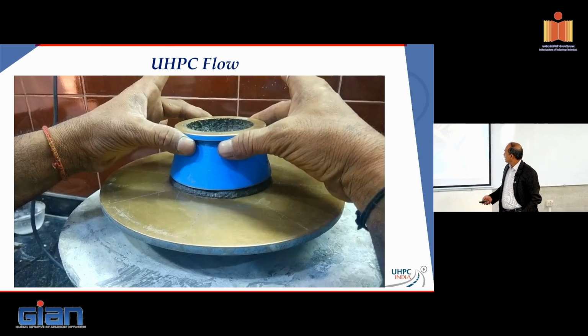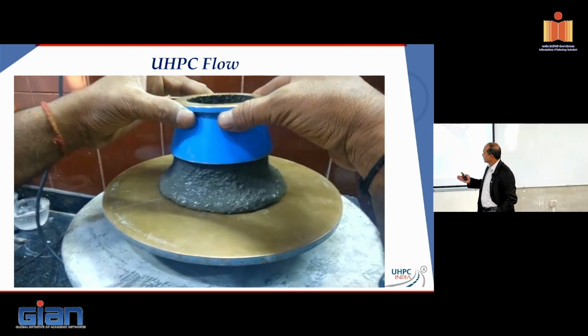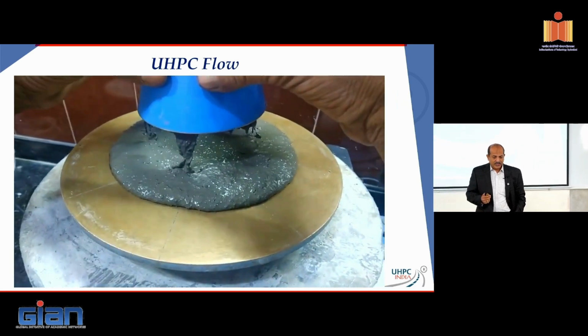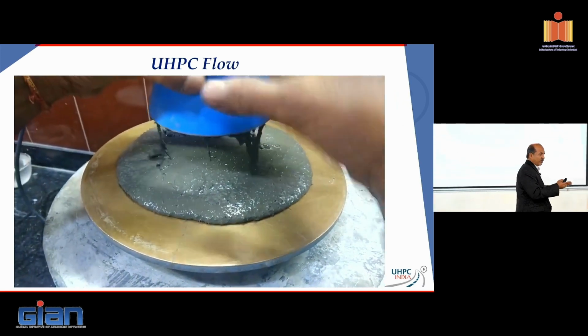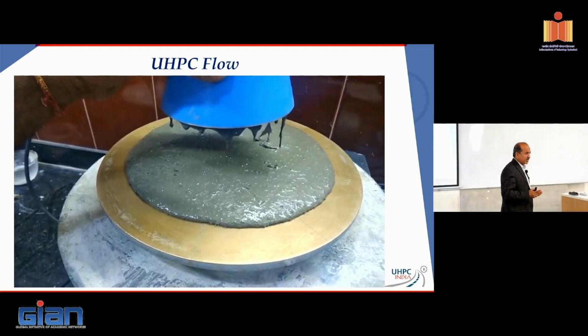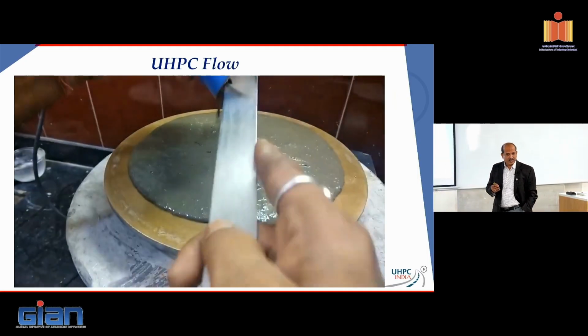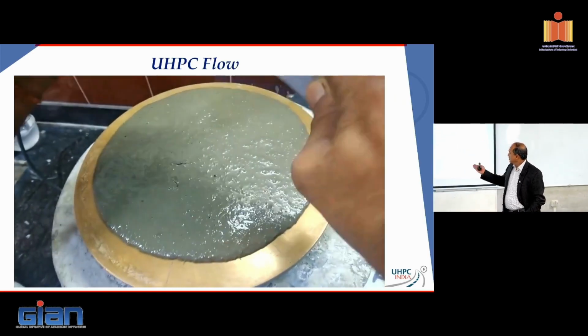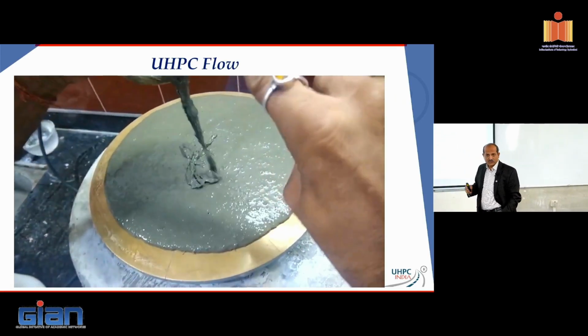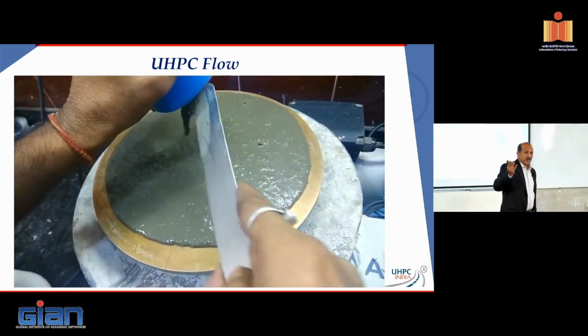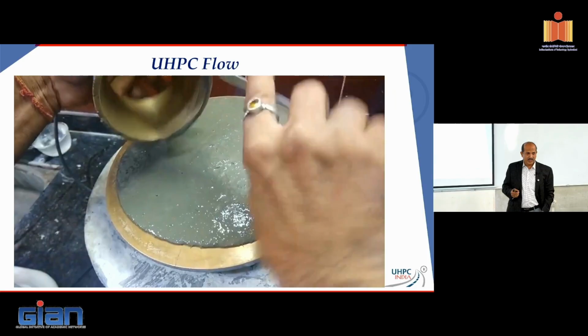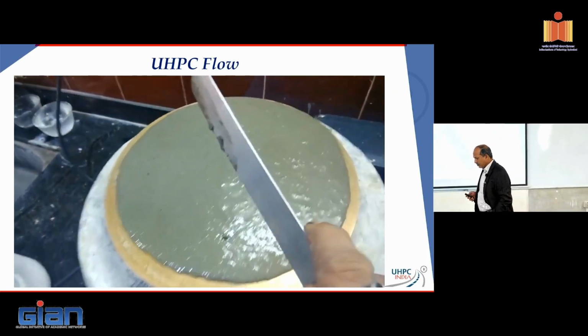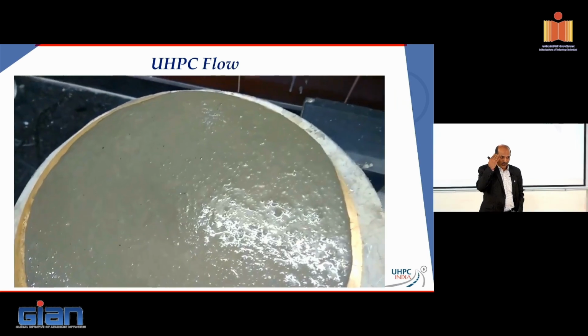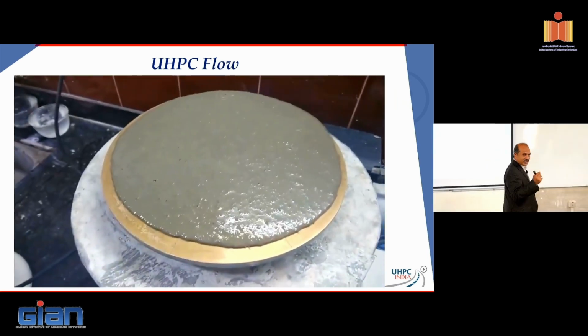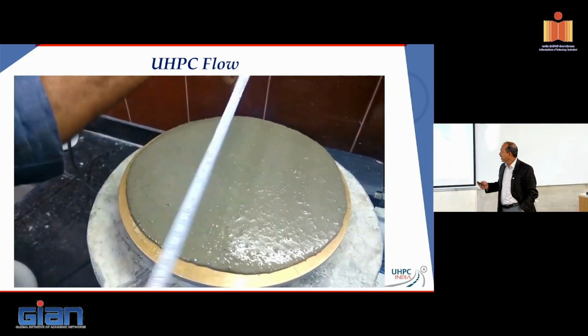And very, very flowable. I start this slide here showing what a typical flow test on a UHPC looks like. It can flow into any kind of mold, any shape that you desire, and it gives quite a bit of flexibility in that manner. You can see that over here, and this has fibers. This has an enormous amount of fibers, at least 2% by volume, which is about 156 kgs a cubic meter of very fine, microfine fibers in it. That's where it comes close to structural steel. It appears as liquid as it could, and it could flow into any kind of system there is.